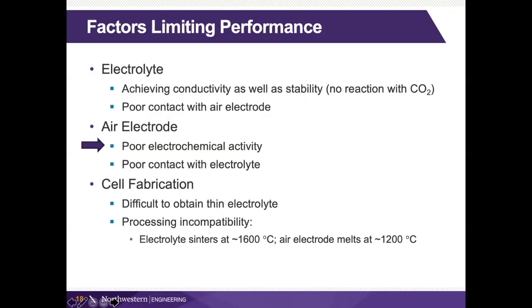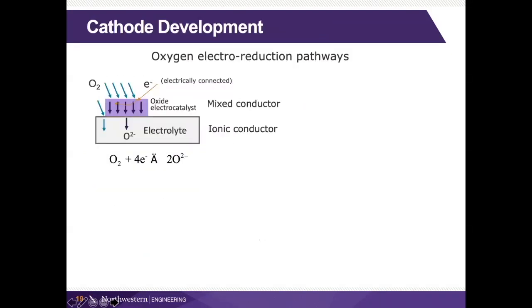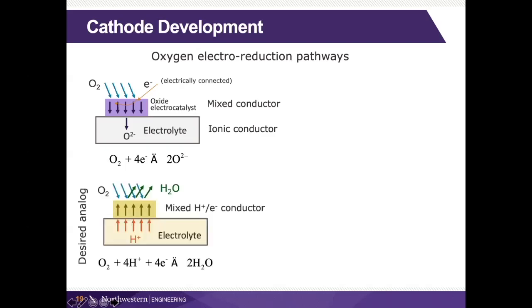Then looking at the poor electrochemical activity of these electrode materials. If we look at what makes a good air electrode or good cathode for the solid oxide, traditional solid oxide fuel cell systems, this is supposed to be an arrow that goes forward and reverse. What we have ideally is a system that does electrocatalysis on its entire surface, as opposed to being limited to just what's called a triple phase boundary. So we want something that can allow oxygen ions through it as well as electrons through it. So we call that a mixed oxygen ion electron conductor. And if it allows the oxygen ions and the electrons to go through, that means we can ideally have catalysis all the way across the surface and we're not limited to what people call these triple phase boundaries.